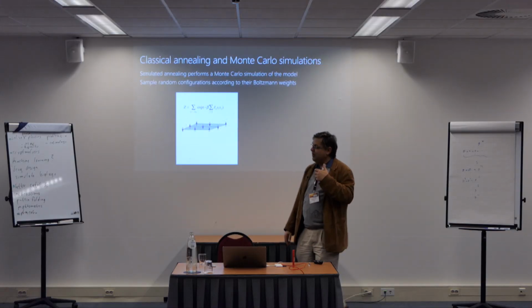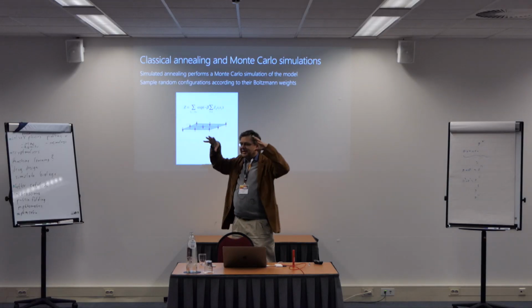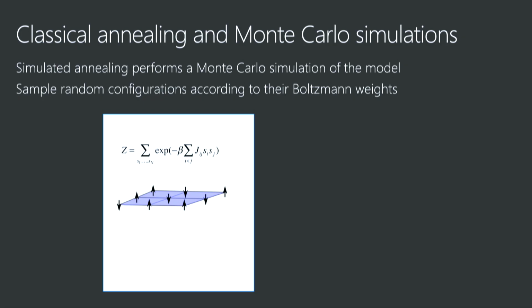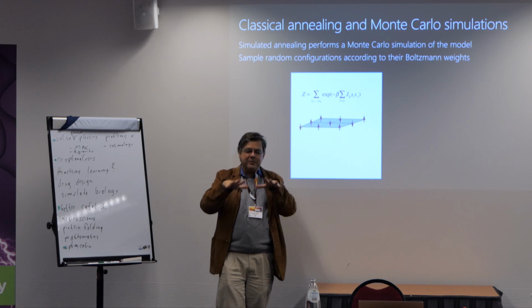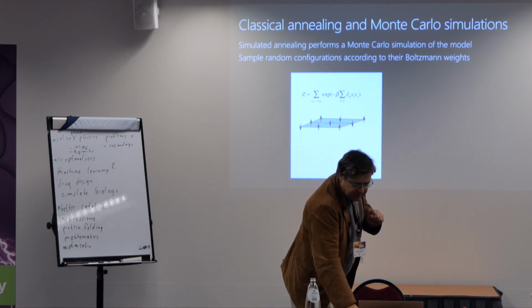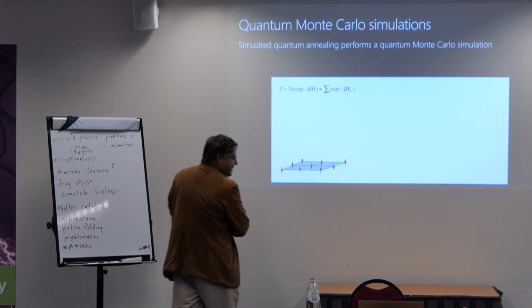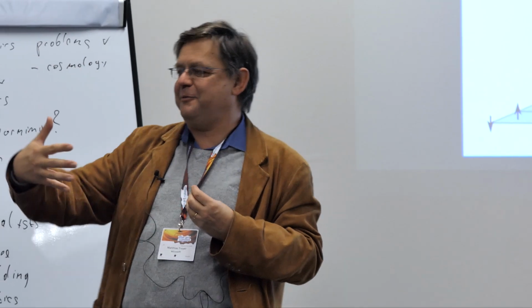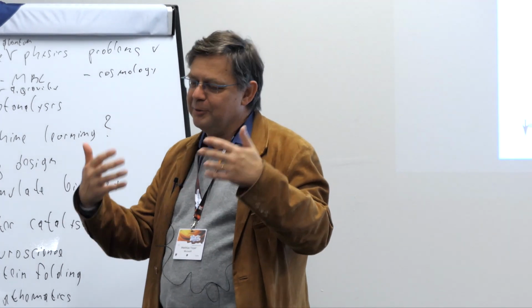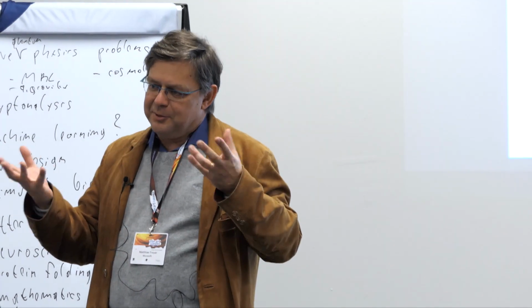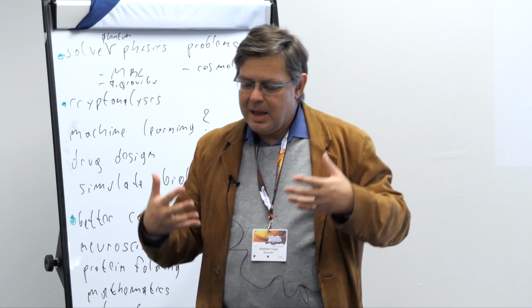And so let me show you how I do classical annealing. Classical annealing is basically I take a system and I cool it down slowly. So let's say I want to find the ground state of my Ising spin glass model. I take my spins, have my couplings, and I simulate it in a Monte Carlo simulation based on the partition function. I flip my spins, I cool it down, and I find the state. If I do it slow enough, then I might find the ground state. If I want to do the same thing for a quantum system, then I take my quantum spins, I put them in this big transverse field, and I simulate it as I slowly reduce the transverse field. And I reduce the quantum fluctuations by reducing the transverse field until I find the ground state.